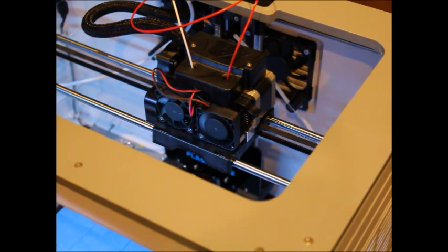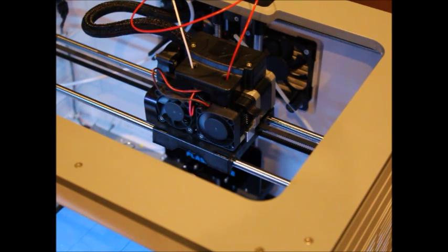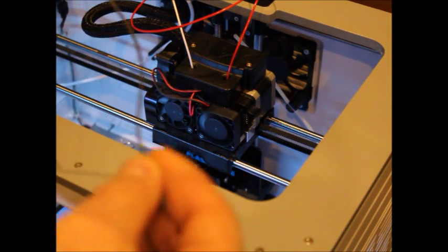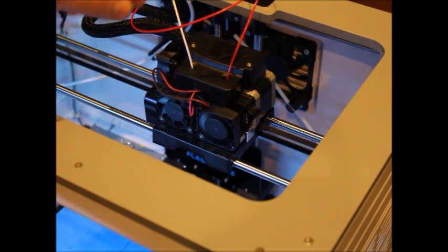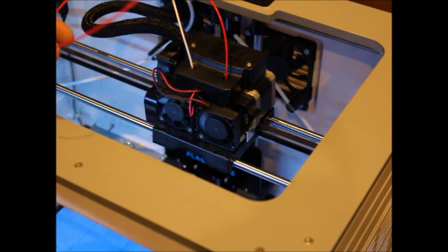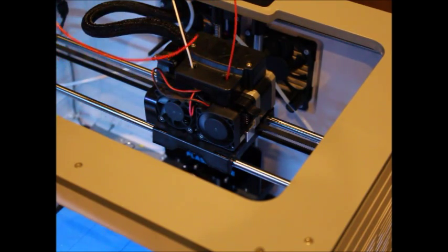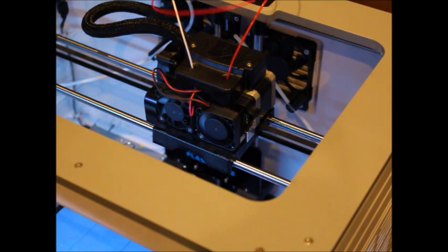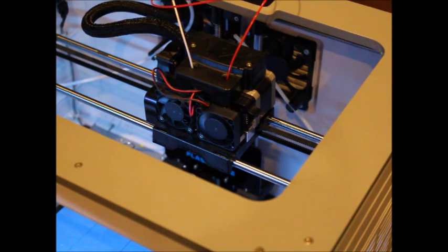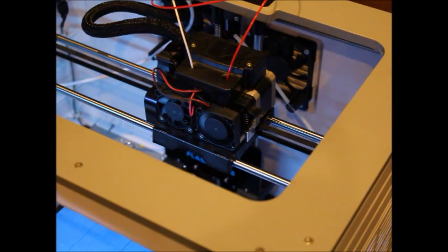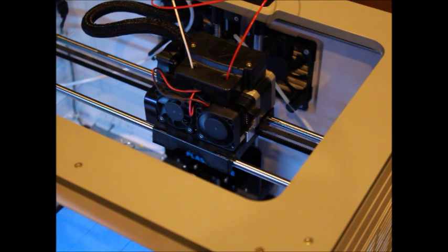Okay, let's have a look at how to load our TPE filament. TPE filament is quite flexible, as you know, and it's quite difficult to feed. And so when replacing the filament, make sure that you have PLA instead of ABS. If you had ABS before printing with TPE, just replace, start extruding the PLA because PLA is softer. And TPE filament, it will be easier for TPE filament to push out the PLA rather than ABS.